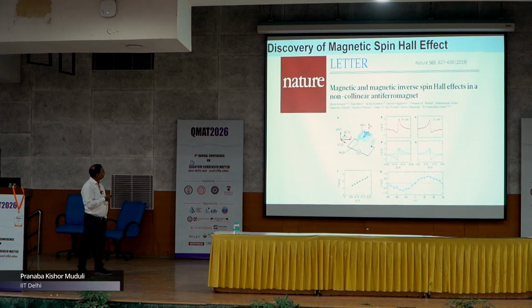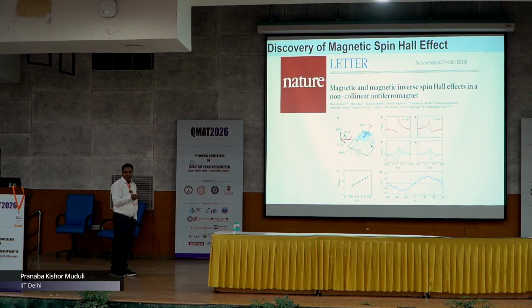And in 2019, a phenomenon called magnetic spin Hall effect was discovered in this material, which is useful for spintronics applications. And this effect you can look at by looking at this green curve. If you look at the shape of this green curve, this is actually positive sign. As you reverse the field, it should actually change the sign, and this sign change doesn't happen, and this is an indication that it's not because of the spin Hall effect, but because of some new phenomenon which they call the magnetic spin Hall effect.